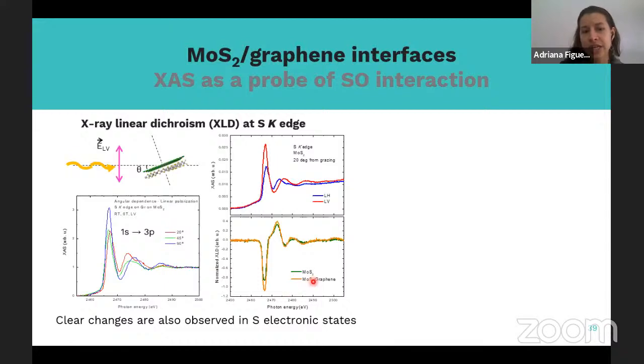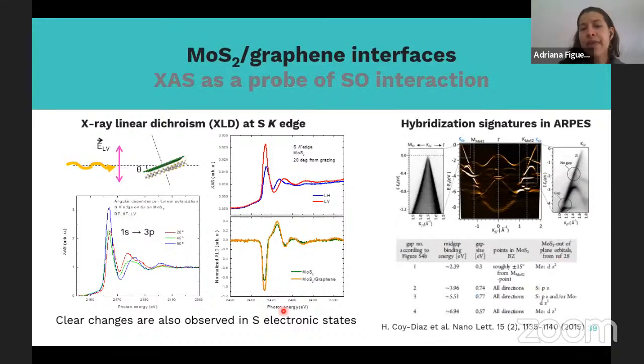We see clear changes with and without the graphene in this case for MoS2, and those are also features that are characteristic of hybridization. Such hybridization has been reported already in ARPES, where they see that indeed there are some features of hybridization between the orbitals.